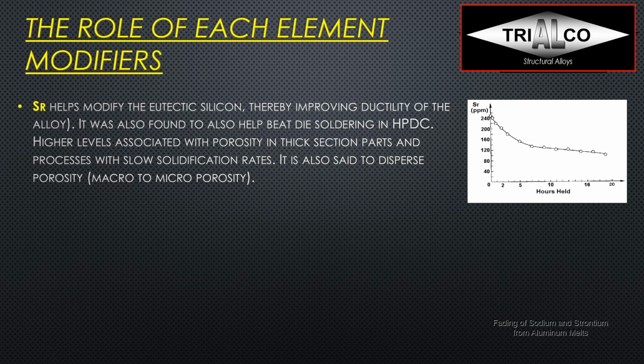It was also found to help beat die soldering in die casting, and higher levels are often associated with porosity in thicker sections of castings, and especially in processes with slow solidification rates. So that's why you often find precision sand casters who do not want to have strontium modified alloy for their castings. But others say, well, it helps disperse porosity and convert macro into micro porosity, which then again is more positive.